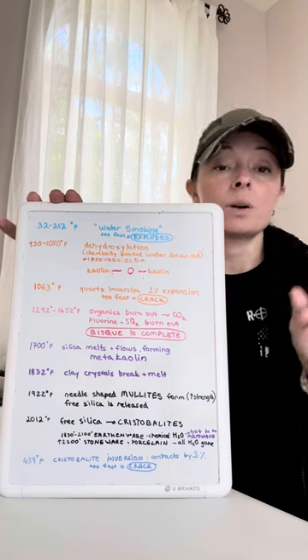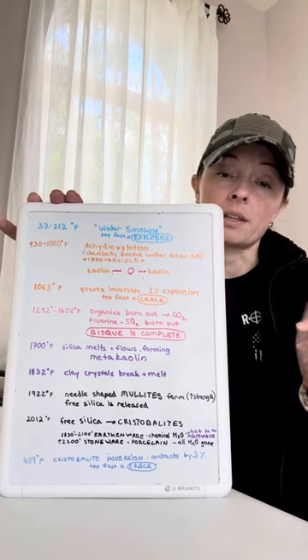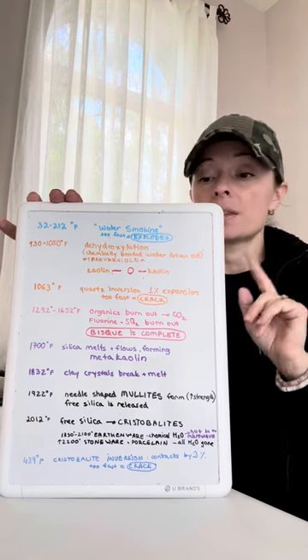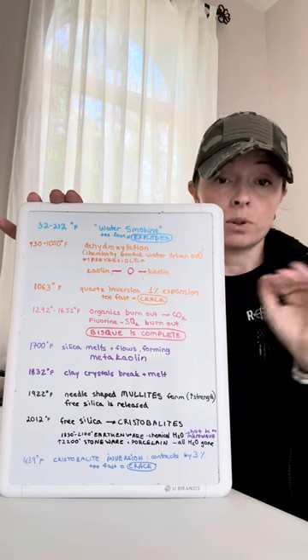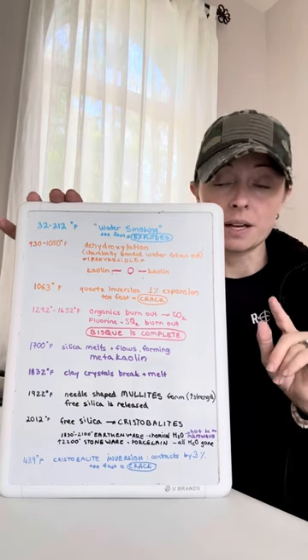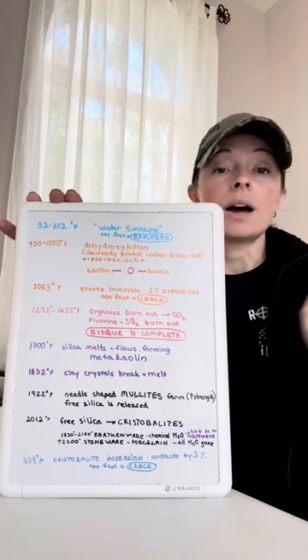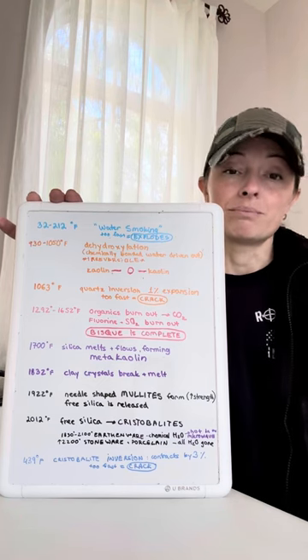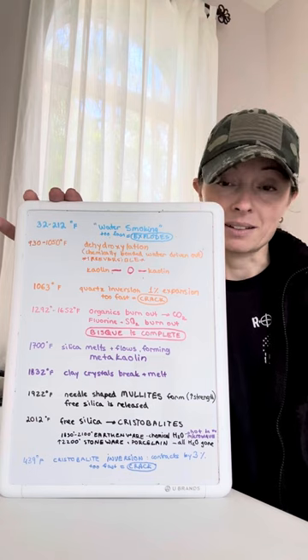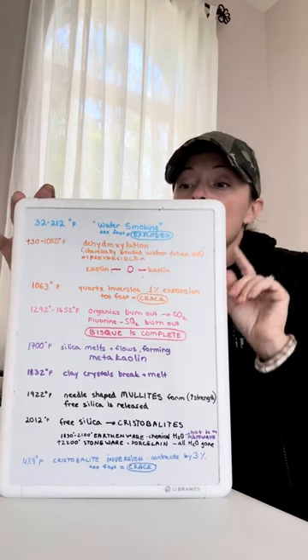So why does that happen? Let me show you how it happens. You'll have to pardon me leaning over. So do you see this? I'm not going to write the full structure for the kaolin molecule because you'll go crazy. But you have kaolin attached to an OH. And on the other side, you have another OH attached to a kaolin. When you apply heat to these bonds here, what happens is this is going to get broken off. And this is nothing but H2O. That is water. And so what's going to happen here is these guys are going to float away. And all you have is kaolin bonded by an oxygen to another kaolin. And that is a much stronger and shorter bond. And that is the process of dehydroxylation, which is driving off chemically bonded water.